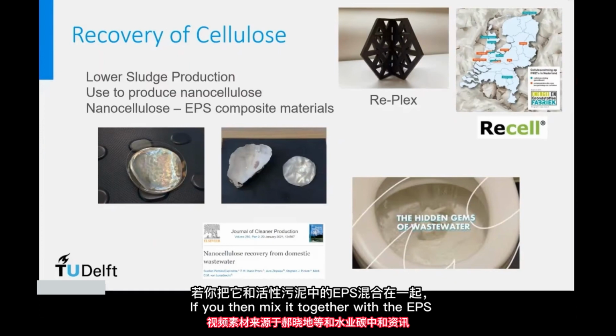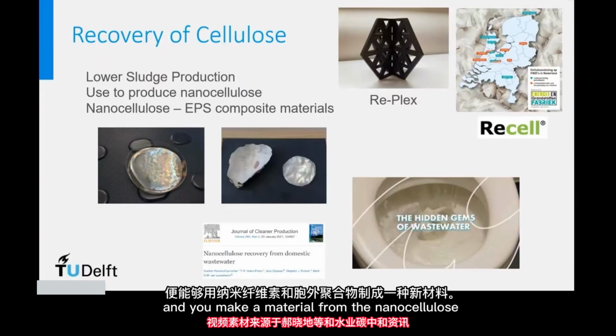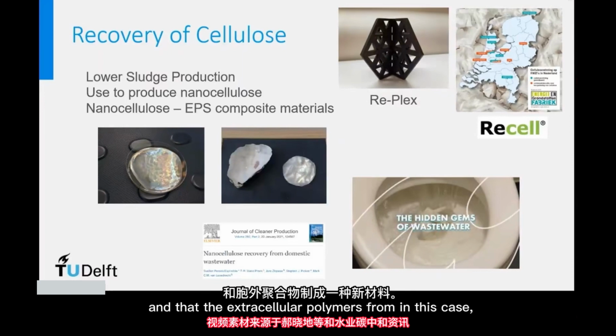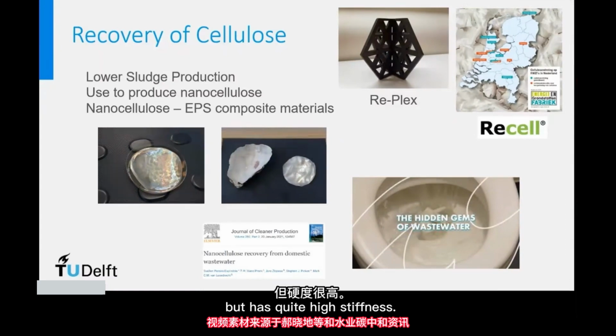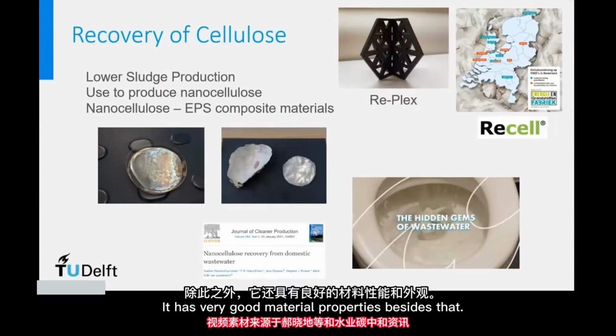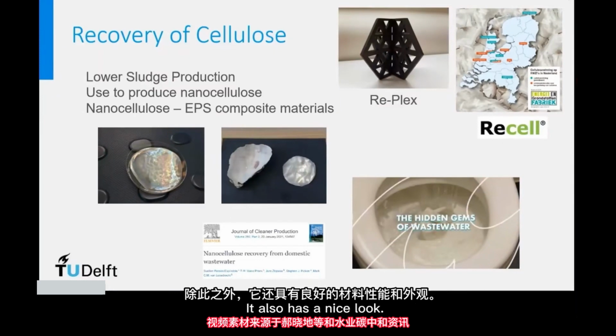And if you then mix it together with the EPS from the activated sludge, and you make a material from the nanocellulose and the extracellular polymers from, in this case, the granular sludge, you get a material which looks very much like mother-of-pearl material, but has quite high stiffness, and it has very good material properties. Besides that, it also has a nice look.